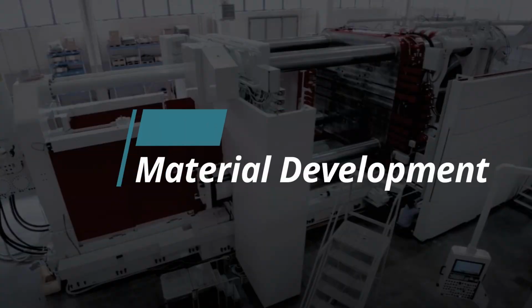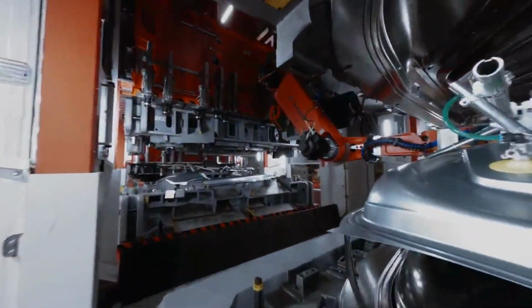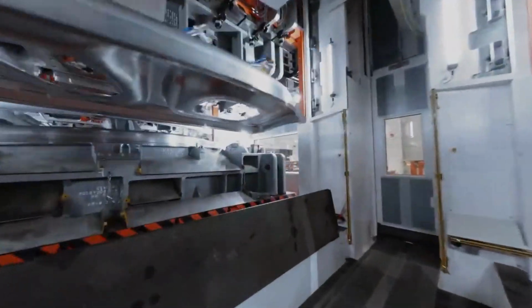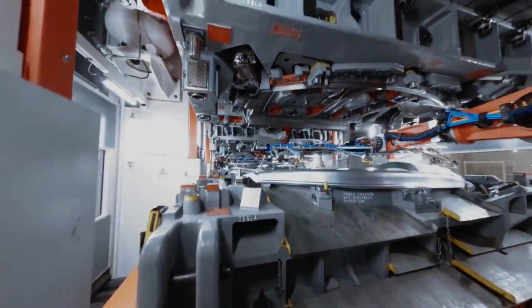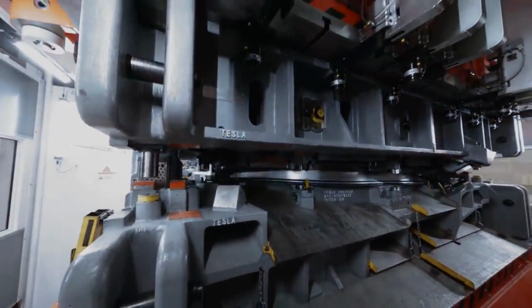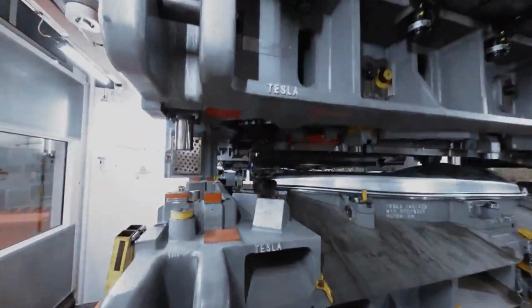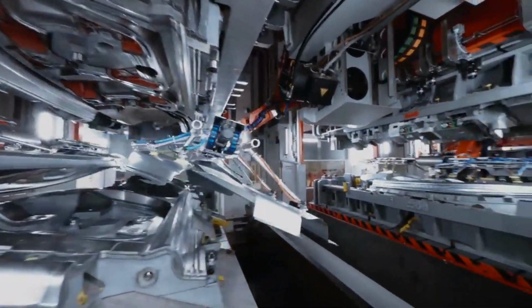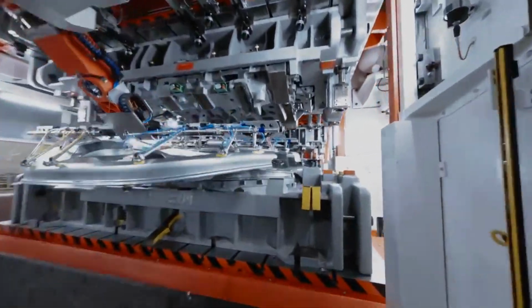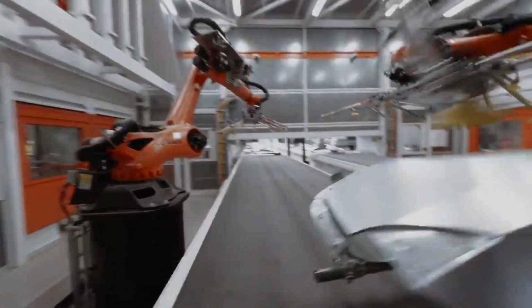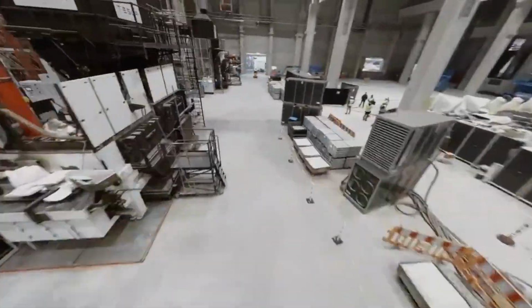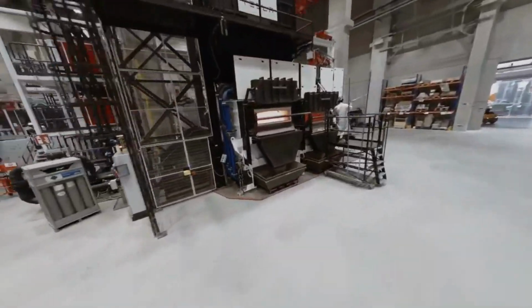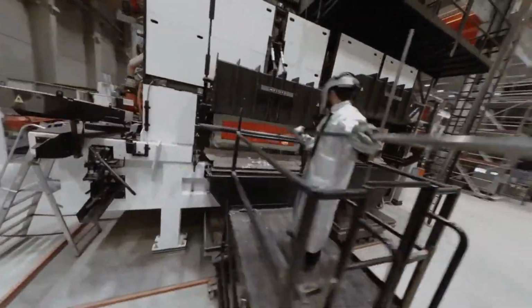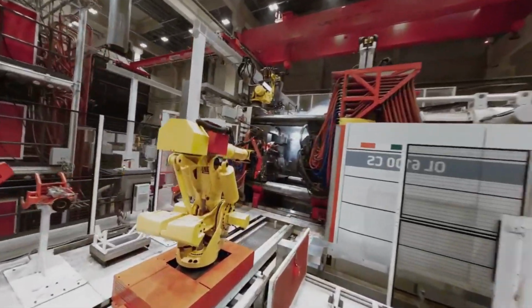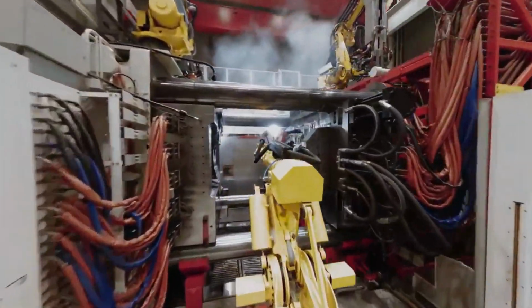Material development. The aluminum alloys and cutoffs from the previous casting cycle must first be melted in an oven at 850 degrees C. The liquid metal is then transferred to another enclosed oven after being cleaned of any impurities using hot pipes. That oven maintains a temperature range of 750 to 850 degrees C. The development of oxides in the molten aluminum is stopped by filling the space inside the storage oven with nitrogen gas. It also helps in keeping the temperature consistent. To further remove pollutants, operators also employ argon gas, a rotary degasser, and a silicon carbide filter.